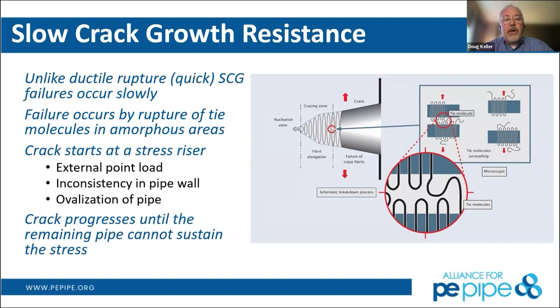of the pipe. And what it does is it actually pulls apart the amorphous regions. So those blue rectangles are actually the crystal structure. And in between those crystals are polyethylene chains. And the simplest way to think of them is Velcro. So the more chains that we can get, the more Velcro essentially between the crystal structures that we can develop, the harder it is to pull those crystals apart, which means that we have much greater slow crack growth resistance and therefore much longer pipe service life.